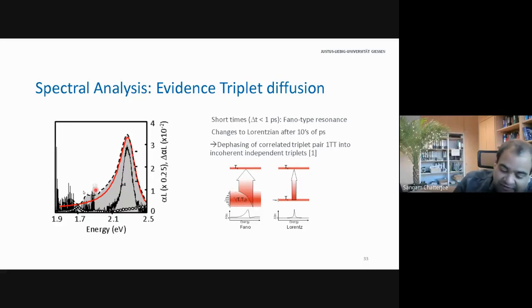Let me come back to the A resonance. The A resonance is also very, very peculiar. What you see here is a Fano-type resonance. Let me remind those of you who don't know what a Fano-type resonance is. This is a phenomenon that you find an asymmetric line shape like you see here in red, which is the origin of an individual transition coupling to a continuum. And this continuum is a correlated triplet pair state. So it's something like a hydrogen molecule which coherently exists. And this coherent state can be in the ground state or can be in the excited state only. And then it diffuses and you get a more Lorentzian line, like you would see here at later times.